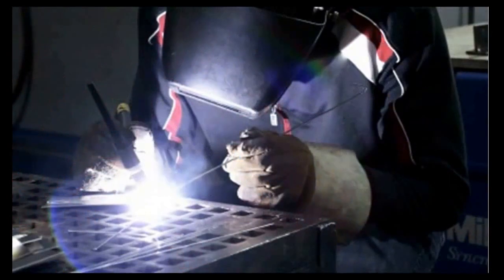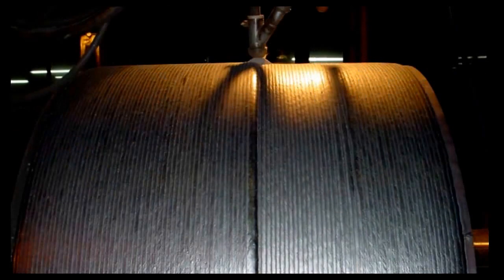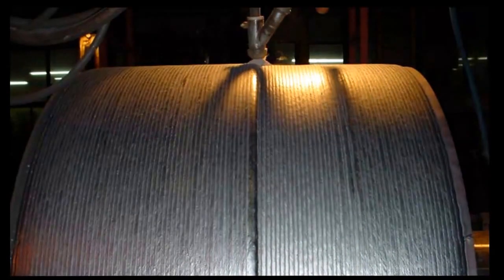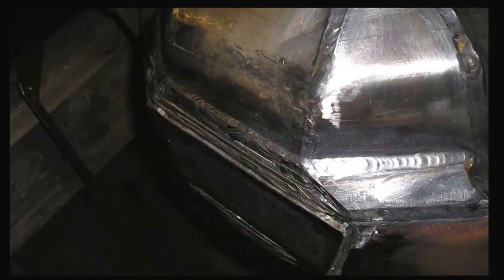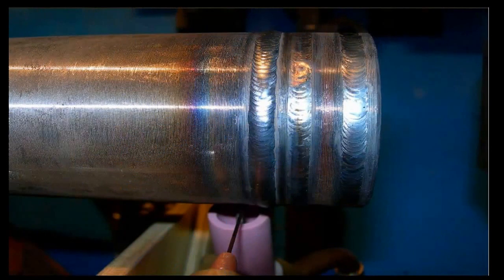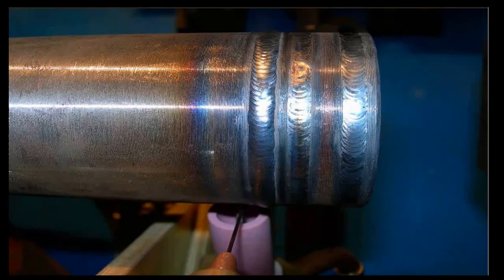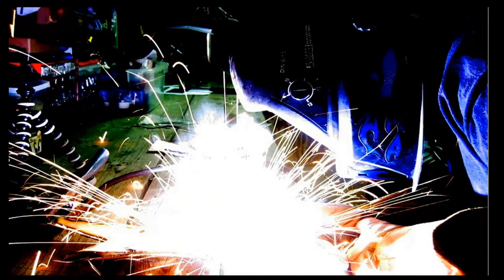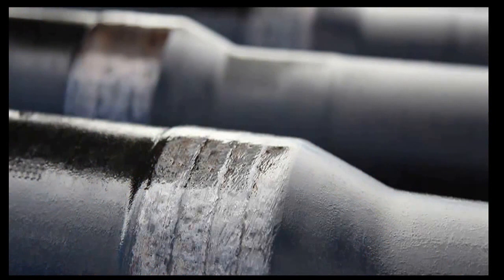Magnesium closely resembles aluminum in appearance. When in doubt, cut a small section from the weld area and melt it. Magnesium will burn with a brilliant white flame, and aluminum will remain a molten globule of metal. Operators hesitate to work upon metal which might burst into flame, but this danger is reduced if Eutectrode 1902 is used with 1902 flux. The flux is a safeguard against overheating, and the alloy is applied below the melting point of magnesium. Eutectrode 1902 is bead forming at lowest application heat and thin flowing when the heat is increased. Use it for sheet and cast magnesium, tubular sections, and aircraft parts.